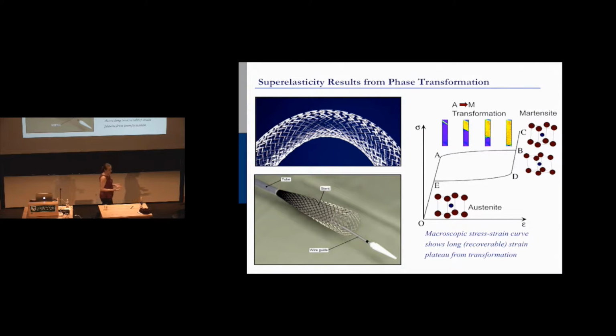So superelasticity is a very useful property. And so you can see there on the bottom, that's the tube being pulled off of the stent that's being deployed out of the tube. The same idea that you're squishing it down. The reason you can squish it down and deploy inside the body is because superelastic nitinol goes through a phase transformation. So you can see you can put very, very large strains on it. It's a weird stress strain curve. And you can recover all those strains. So you can really crank it down and release it, and it'll come back.